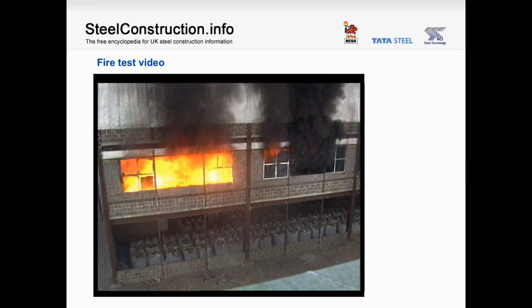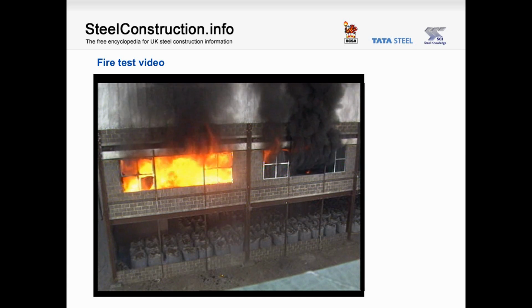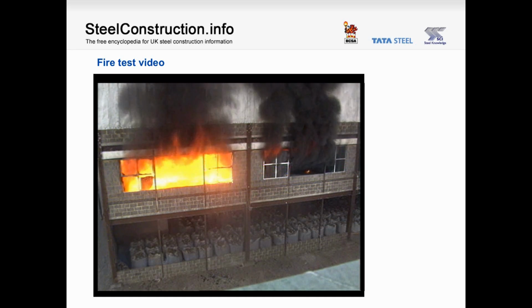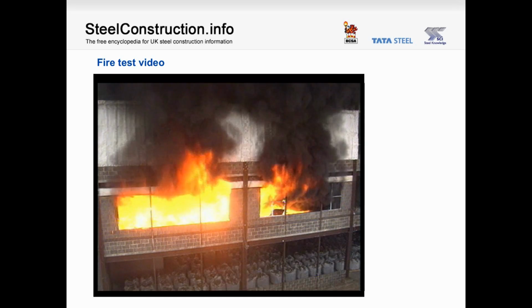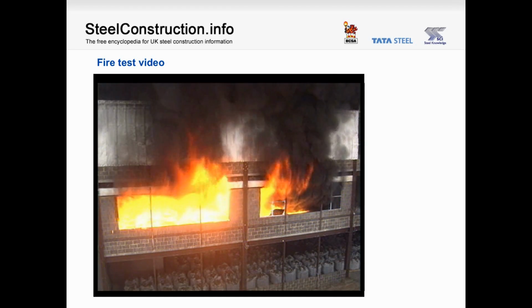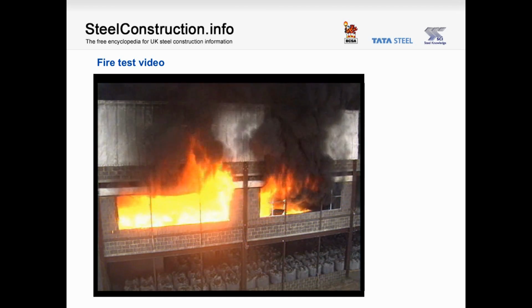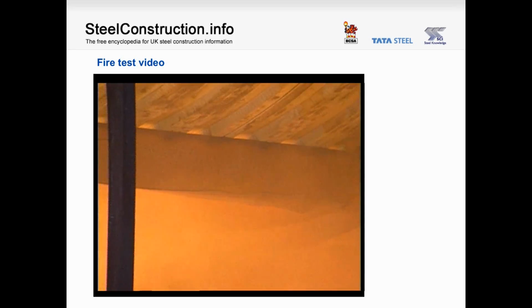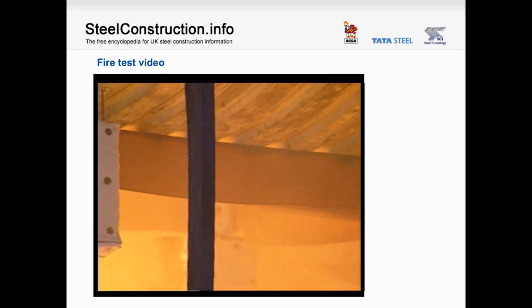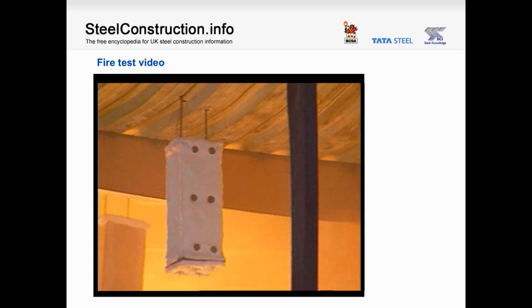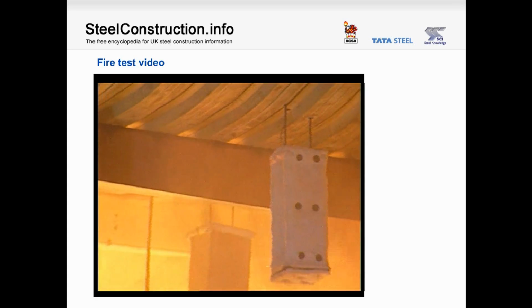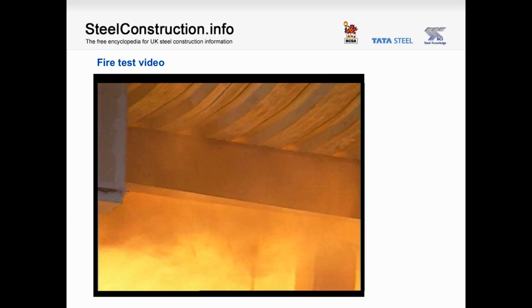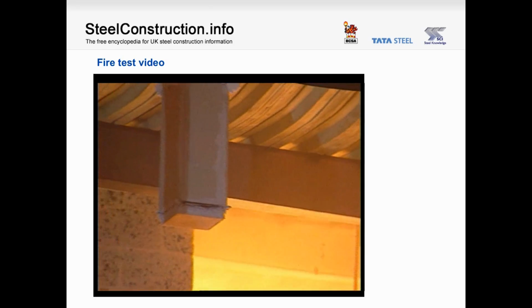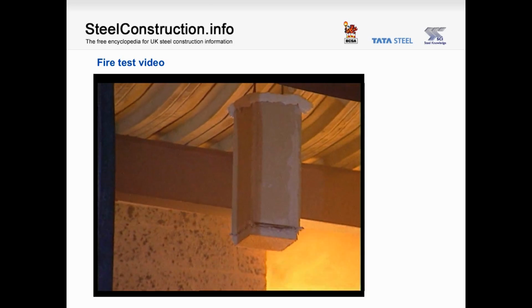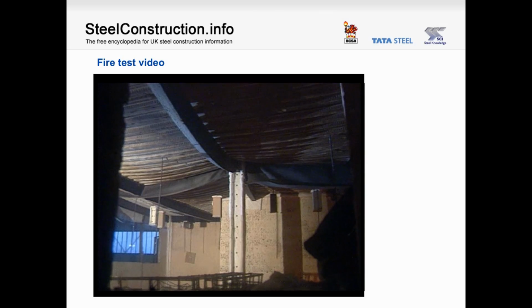This is characterized by spontaneous combustion within the compartment. There are a number of different forms of flashover, and it often occurs when temperatures at ceiling level reach about 600 degrees centigrade. You are looking here at a post-flashover condition. The temperatures in the middle of the compartment at this point are about 1200 degrees centigrade. This is about 450 degrees centigrade higher than the maximum temperature which occurred in the fire at Basingstoke, which we saw at the start of this presentation.